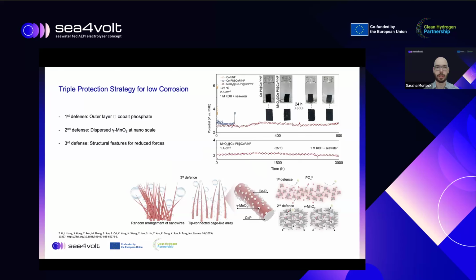One example here in the literature is where they use the triple protection strategy to reduce the corrosion, where we have an outer layer of cobalt phosphate, then there's a dispersed γ-MnO2 at nano scale, and finally a third defense mechanism is to use a special structure to reduce the forces that are caused by the bubbles. If you apply just one of these protection mechanisms, you can see that there's a degradation that happens rather soon. If you have all 3 mechanisms, you can run at a constant voltage for about 3,000 hours. Next slide,